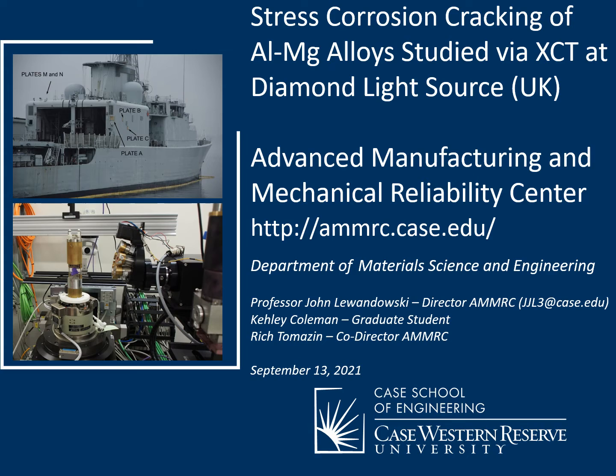As shown in the top left, what we have in our possession are plates that have been retrieved from a Navy destroyer after 42 years of service. As shown in the bottom, we've been testing some of those samples at the Diamond Light Source in the UK, where on the left, we can test in tension, but in different atmospheres, in the beamline and record the evolution of fracture, either under dry or stress corrosion cracking conditions.